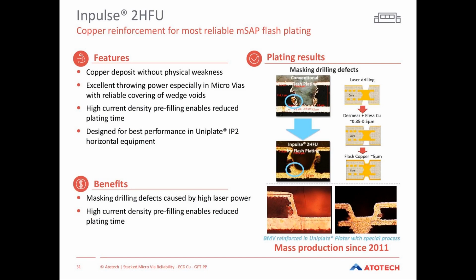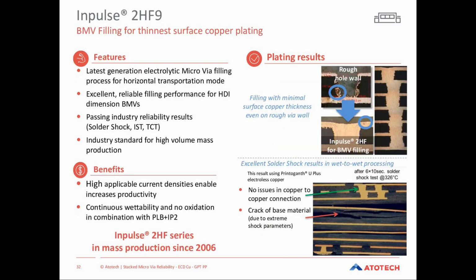For horizontal processes, we have meanwhile developed a pre-plating process for flash plating, or especially for MSAP application here. This new horizontal flash plating or strike plating process is excellent even for microvias which are maybe not perfectly drilled and where we have glass fiber protrusion and other irregularities at the hole walls. We can level the microvias very well with this newly developed horizontal flash plating process, so that we have a good precondition for later copper filling, that the copper filling will be inclusion free and also undisturbed during nucleation.